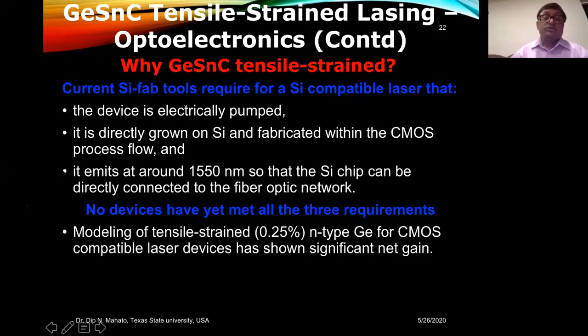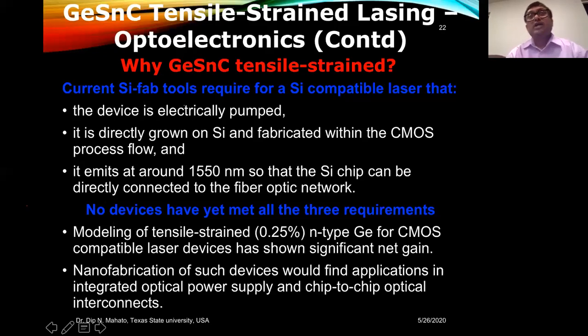So then the question is, why only 0.25% strain? The data so far shows that if you have 2% tensile strain germanium, then the germanium has two band gaps, direct band gap and indirect band gap. At 2% tensile strain, it becomes the direct band gap, and then you are done. But another challenge is, when it becomes the direct band gap, the light you get is 2500 nanometer. It's not 1550 nanometer. So another requirement is you have to have 1550 nanometer so you could connect it to the fiber optic network. That doesn't meet it there, and that's the reason you have to make sure you get what you want.